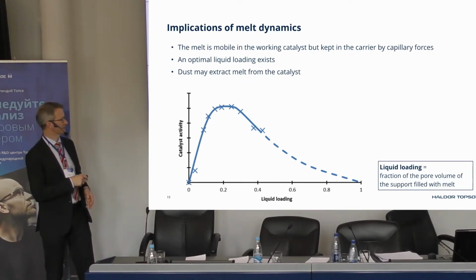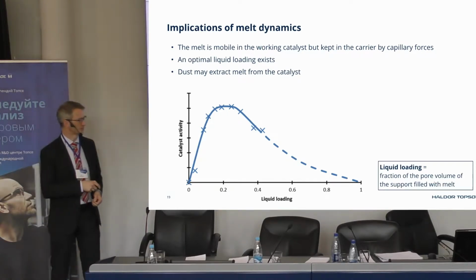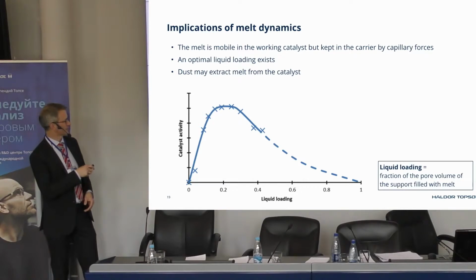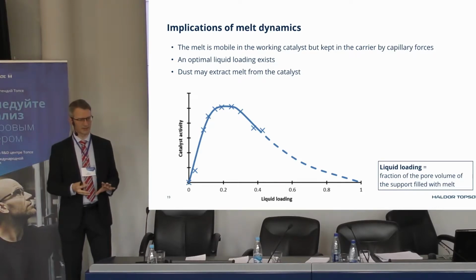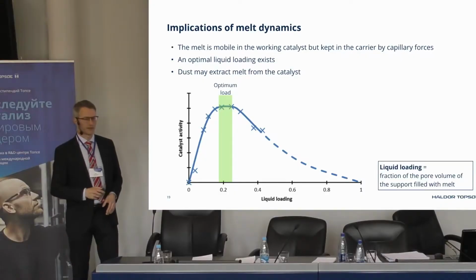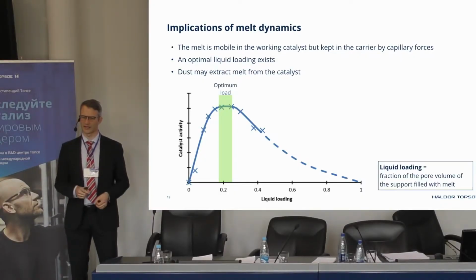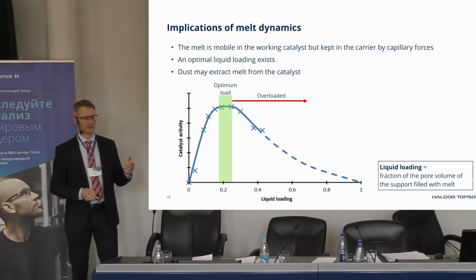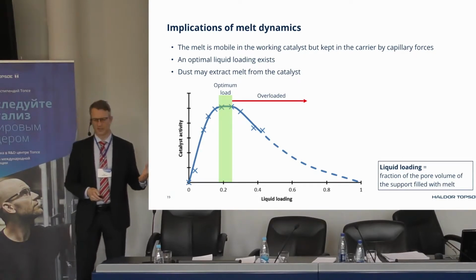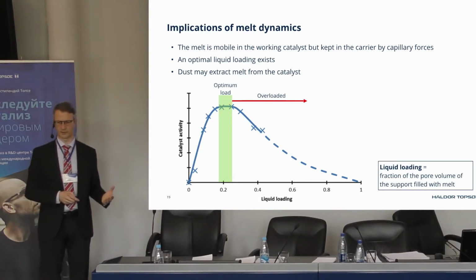If we plot here the catalyst activity as a function of the liquid loading, which is the fraction of the pore volume filled with the active phase, we see some proportional effects at low loading. But if we have high loading, we get poor gas transport in the catalyst, and then we get a lower activity. So there's an optimum liquid loading for this catalyst system, and more vanadium is not always better, because you can actually get a lower activity if you overload.